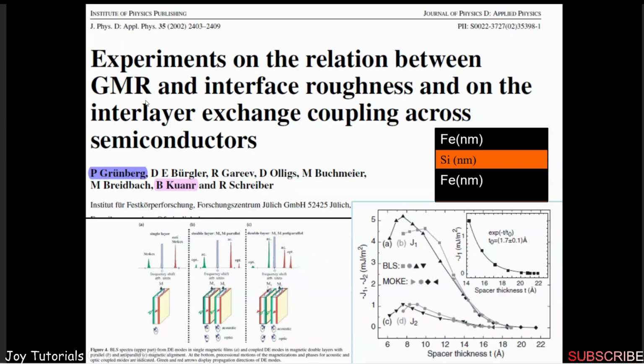In this work, we try to explain the experiments on the relation between the giant magnetoresistance and the interface roughness. As I said at the beginning, the GMR is a surface effect as well as a bulk effect. How the interface is going to regulate the GMR value depends on the interlayer exchange coupling. Through the interlayer exchange coupling, one can manipulate the GMR value through iron silicon, but then it is not a GMR, it is a TMR, since it is an insulator now. Through Brillouin light scattering and magneto-optic Kerr effect experiments, one can understand what kind of interlayer exchange coupling is there, and through this one can indirectly say how much GMR value there is.